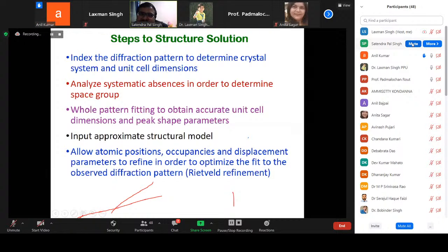First, you have to index the system to obtain the unit cell dimensions. Once you index the system, you will have the unit cell parameters and all the planes present in the XRD pattern. So you will have the hkl values, and by seeing those hkl values, you will be able to analyze systematic absences to determine the space group. Once you get the lattice parameters and the crystal system, you can go for the whole pattern fitting, that is called Le Bail fitting, and then obtain accurate cell parameters. After that, if you know some input structural model, then you input it and go for the Rietveld refinement.